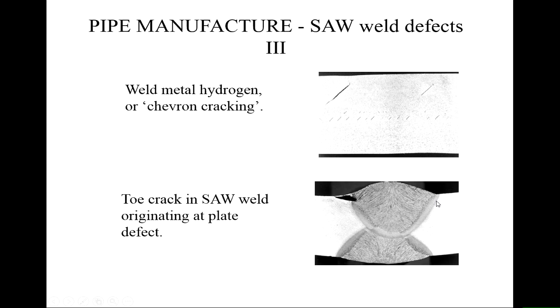Not all defects come from the welding. Here is a case here where we have a defect at the toe of this weld, but that defect was a lamination in the plate originally. It wasn't actually something that was introduced during welding. And you can tell that because we've got this sort of scab of material being lifted up off the top here in a very large hole. And normally the stresses here are tensile that would stretch that downwards and would close those sorts of defects up. So that's a pre-existing defect in the plate rather than anything else.